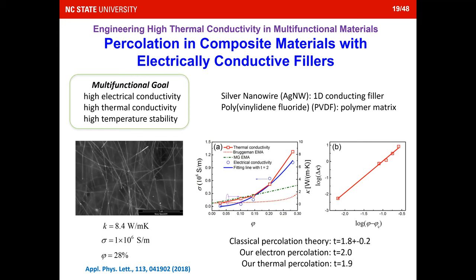And then we choose the matrix that can sustain high temperature, which is the PVDF. Another reason we choose this is because it can disperse silver nanowire quite well. So we measure thermal conductivity and electric conductivity as a function of different concentrations. And what we find is that it seems like we observe that percolation behavior, because you have an increase of the electric conductivity and thermal conductivity quite a lot with higher and higher volumetric concentration.